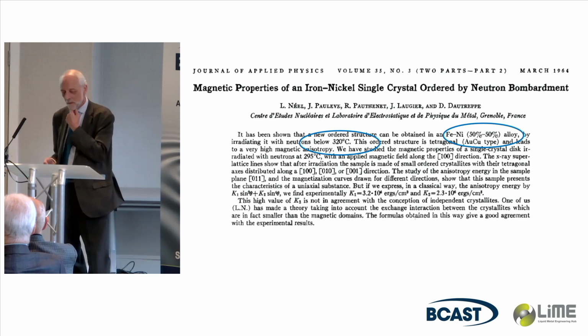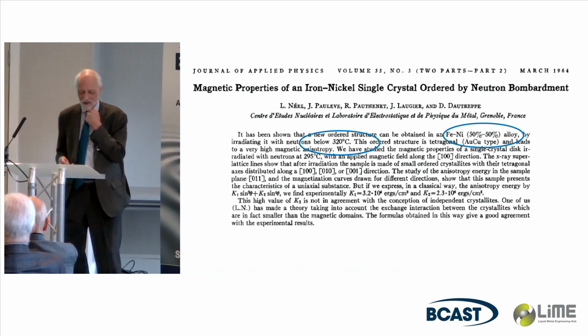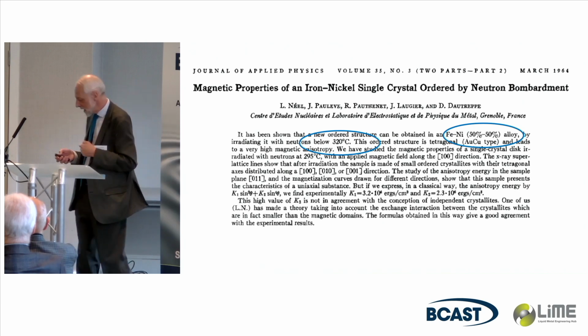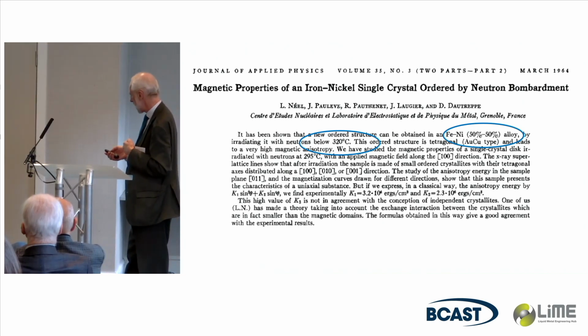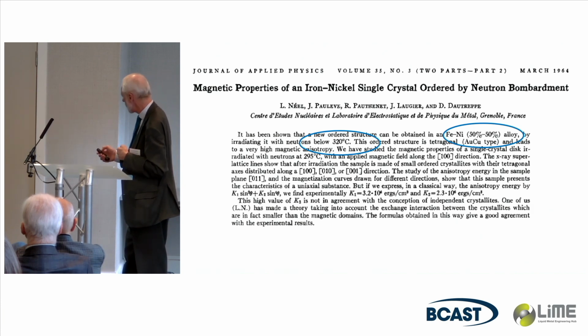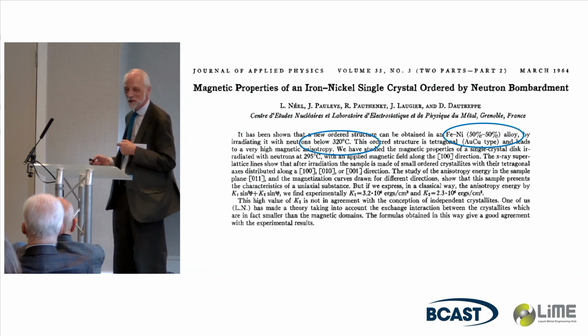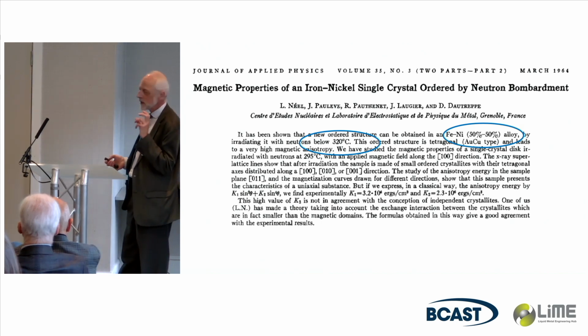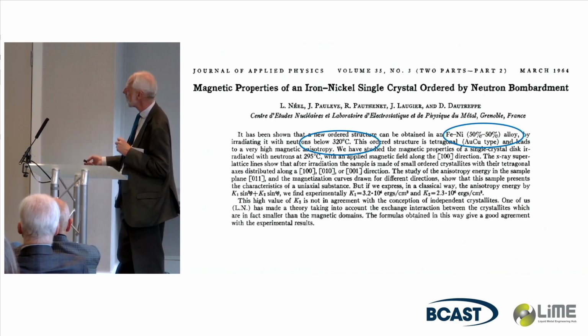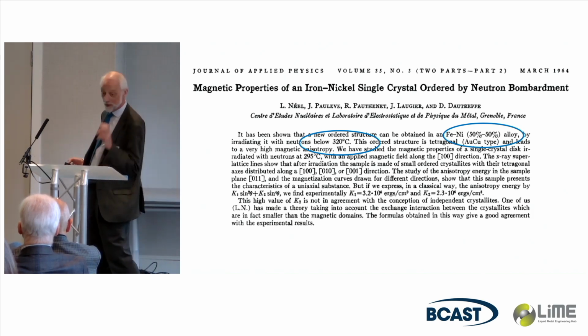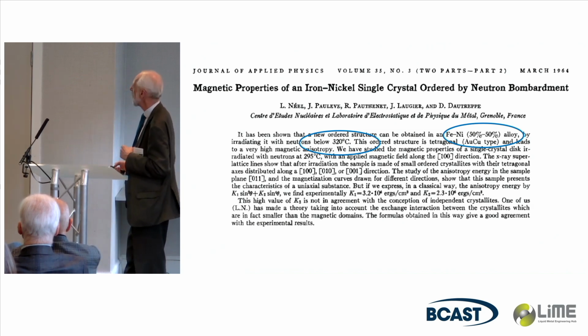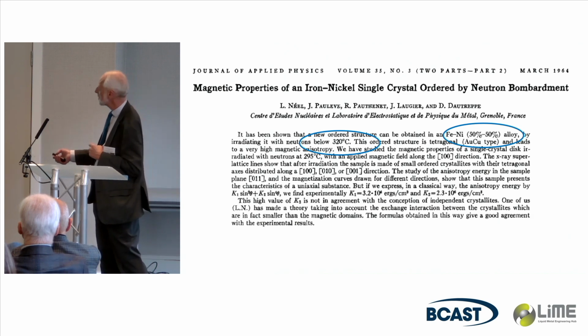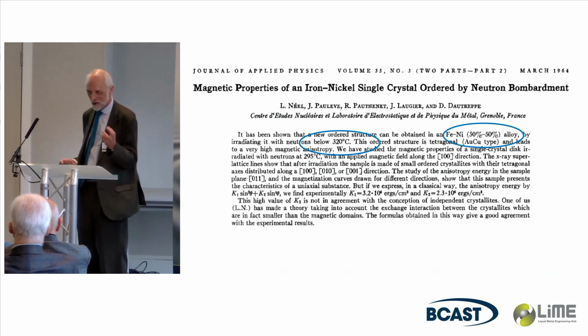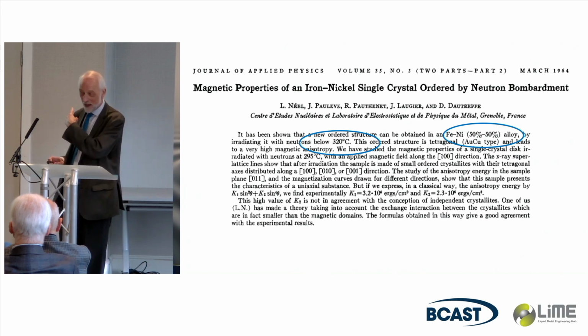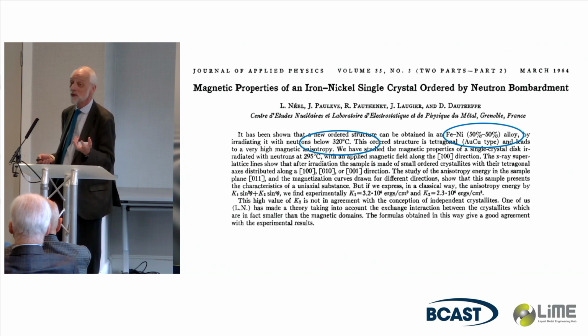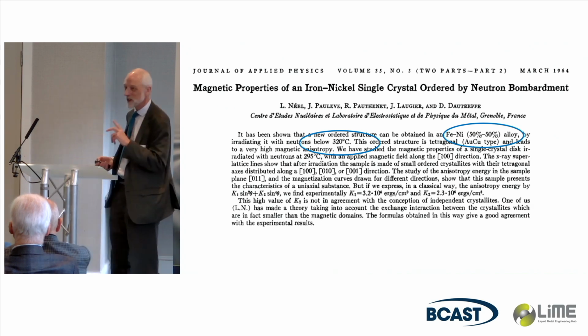Now I'll take you away from that story back to the 1960s and none other than Louis Néel. And his group in Grenoble was looking at 50-50 iron-nickel, which of course you will realize is a very simple crystal structure, FCC. But they figured out that below a critical order disorder temperature of about 320 Celsius, it would order chemically within the FCC lattice to an L10 structure. But of course 320 degrees C is not a very high temperature for iron-nickel. The atoms are not mobile. If you waited for them to order at that temperature, the mobility would mean you could achieve it in between 2 and 10,000 years. So how to accelerate it?